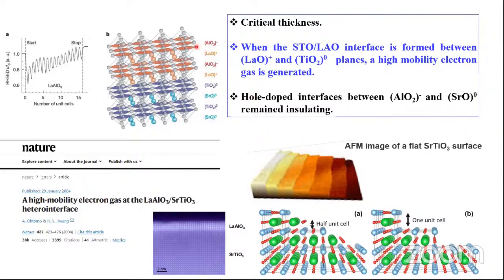And also there was a dependence on the critical thickness of the lanthanum aluminate layer that was grown on top of strontium titanate. Only when the thickness of the LAO was above 4 unit cells, the two-dimensional electron gas formed. And how many unit cells are deposited can be counted by counting the number of peaks in the RHEED pattern, which is done in situ during the growth of the LAO layer. And these interfaces are actually quite sharp.